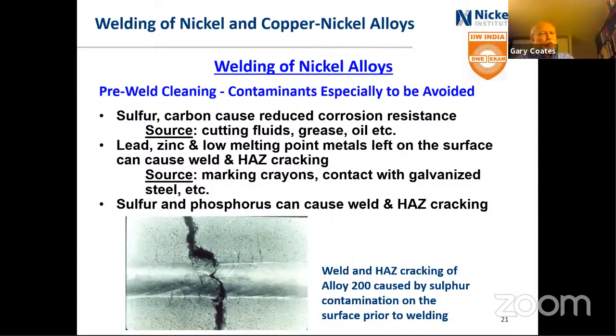Cleaning, we said, is important, and sulfur and carbon can reduce the corrosion resistance if they're in the weld joint or beside the weld. Low melting point metals from marking crayons, lead, zinc, etc., left on the surface can cause cracking. And contact with galvanized steel is another example of that.